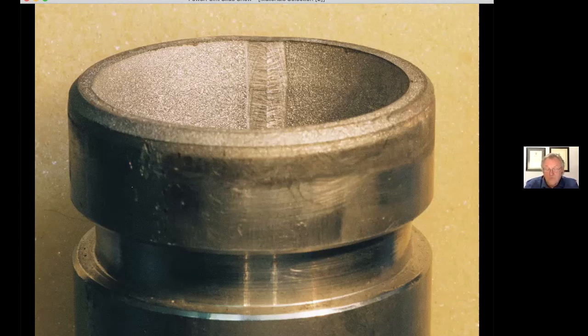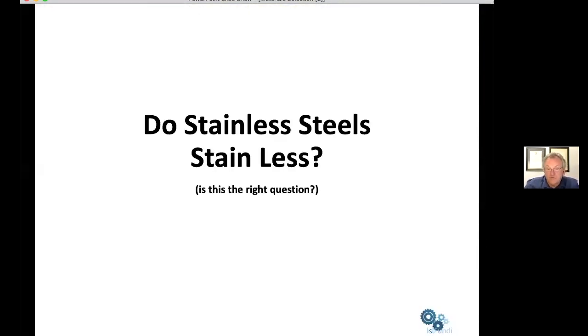And it was sufficient to break down the passive layer of this very expensive material and cause it to corrode quite drastically. We've also seen similar situations with these very high alloy materials in things like electrolytic chlorinators, where systems have not been properly earthed, and you get stray currents flowing through process plants, which can cause this sort of corrosion.